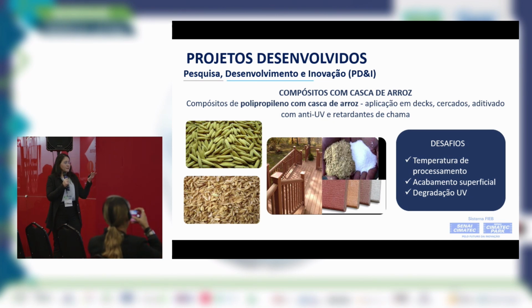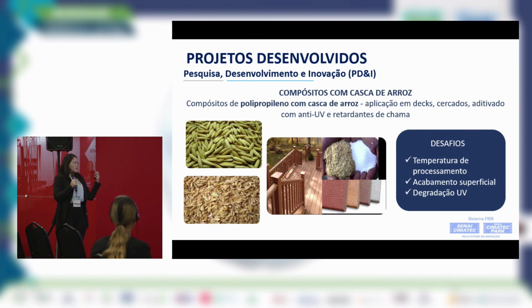Well, polypropylene composite using rice hull to be used in fences and decks, boards. So we had to use additives in this composite with an anti-UV light agent, and also flame retardants had to be used, because the civil construction industry requires that, because most of the products that use polymeric materials need to have the flame retardants added. The key challenges were the processing temperature, because the rice hull is quite sensitive to temperature. So depending on the process, we may degrade the peel, the hull of the rice. That's an issue, because instead of a fiber, it becomes carbon in there or coal in there.